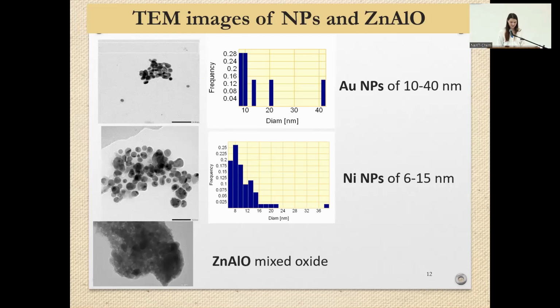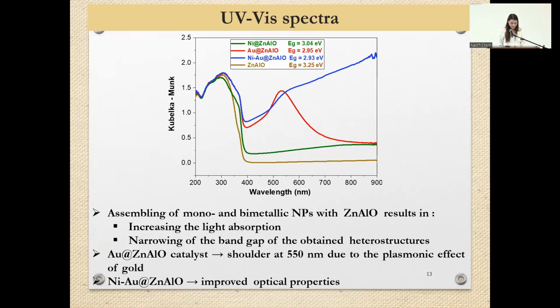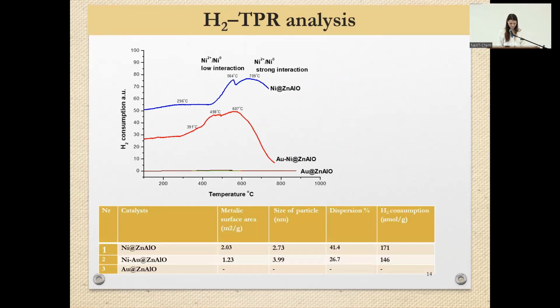The TEM images of the nanoparticles indicate a morphologic and homogeneous distribution of the mixed oxides, as well as a good distribution of the diameter of the nanoparticles. The assembling of mono and bimetallic nanoparticles with zinc aluminum oxide results in increased light absorption and narrowing of the band gap of the obtained heterostructures. For the gold catalyst, we see a specific shoulder at 550 nanometers due to the plasmonic effect of the gold. And for the bimetallic catalyst, we see an overall improvement in optical properties.